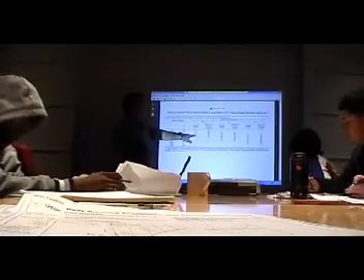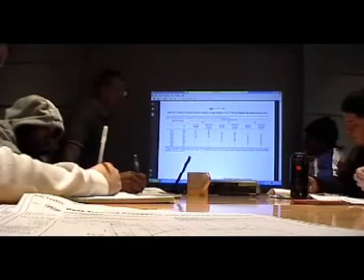I could, if the hardness is above 75 on the 15T, it's a legitimate number. If it's above 72 on the 30T scale, it's a legitimate number. If it's above 71 on the 45T scale, it's legitimate. Technically, they're telling me I can use all three scales. What you normally do is you use the lightest scale and see where you're at.